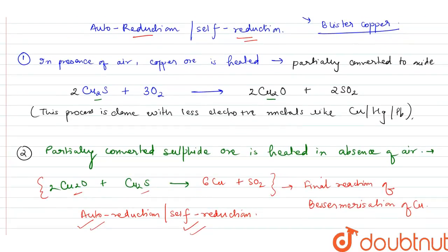The first part is done in an aerobic atmosphere — in the presence of oxygen — to partially convert the sulphide ore to oxide, so that both oxide and sulphide ores are present. After that, self-reduction is carried out to give pure copper, known as blister copper, and SO₂ is given out. I hope you have understood all the points well. Thank you.